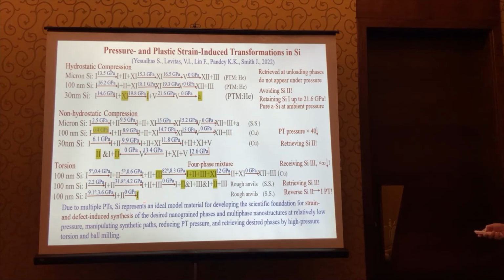Then silicon 1. Nobody could receive reverse phase transitions from silicon 2 to silicon 1. It transforms to different phases. Again, we were able to manipulate paths and obtain it. Now, even under hydrostatic condition, look which phases we have. 1, 2, 11, 5, but during unloading, 12 and 3, so completely different phases. That is why post-mortem study of these phases gives us nothing about what happens under pressure. That is why in situ study is very important.